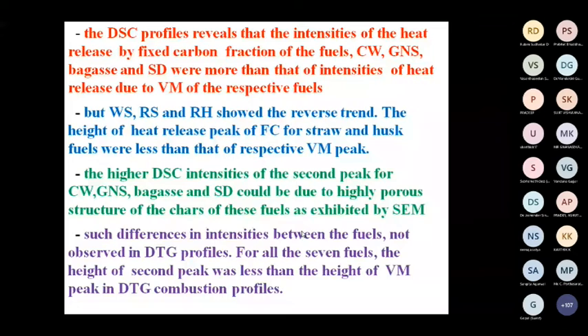If you compare the rice husk, rice straw, and rice husk, this is different. If you see a SEM picture, you will understand. Because of the highly porous structure, heat release from the other wastes, bagasse and sawdust, is so quick for fixed carbon. That is why the intensity is going high. Such differences in intensities between the fuels were not observed in DTG. In all the 7 fuels, the height of the second peak was lesser than that. Because of the highly porous structure of the char particles, the heat release is at a much higher rate. That's why we are seeing the difference.